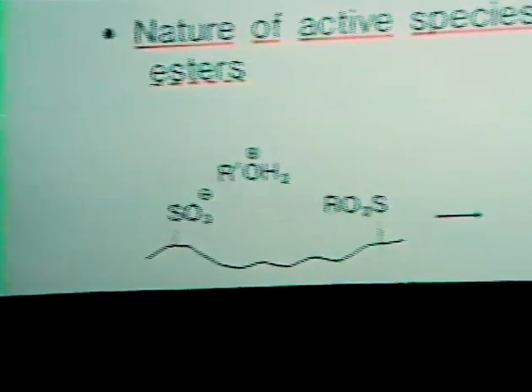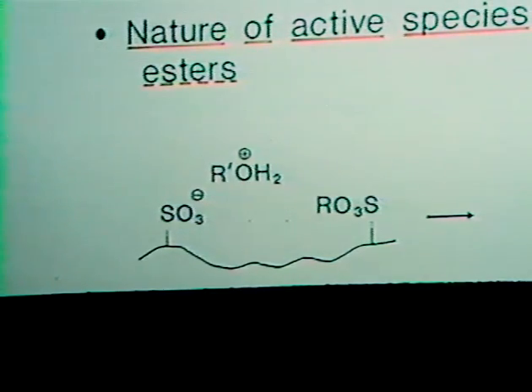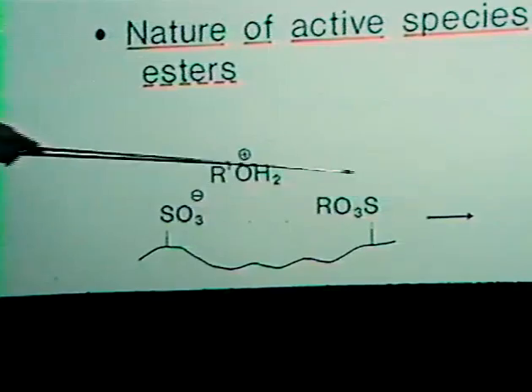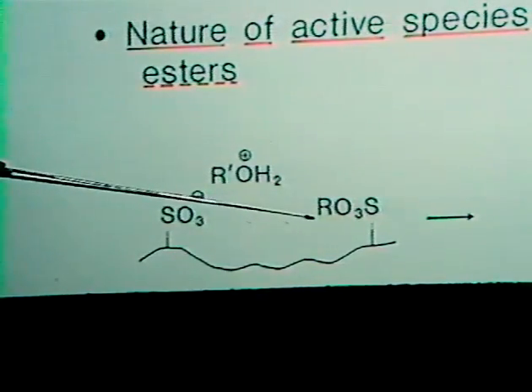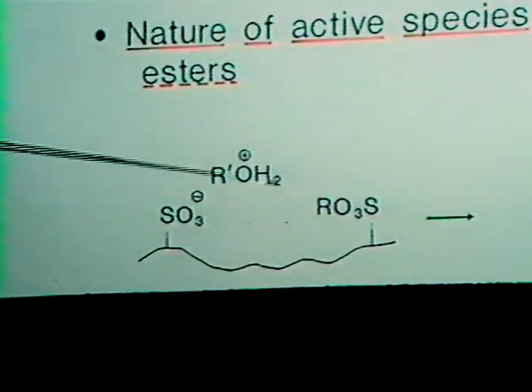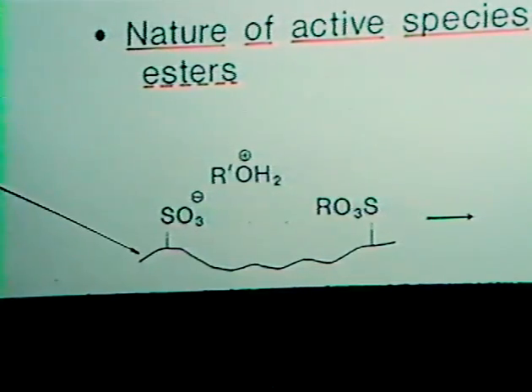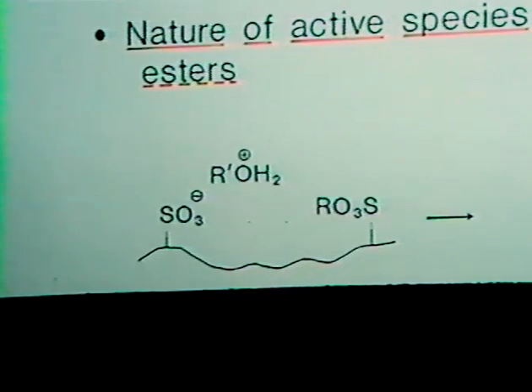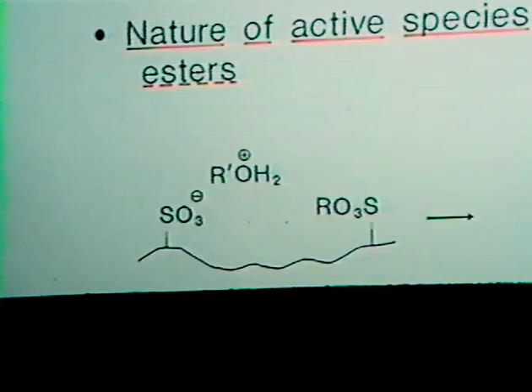The second thing that the alcohol can do with the SO3H group is to make an ester. If I have two esters, how do I make an ether? I make an ether and anhydride of two SO3H groups, possibly so. But our momentarily preferred mechanism is such that in fact one of the two alcohols, isobutanol, makes the ester. The oxonium is of course a precursor of that ester, but it reacts in the ester form with the oxonium of methanol, which sits on its counter ion. And this reaction is easily written in terms of either a concerted or stepwise process to give you the mixed ether and two SO3H groups, which regenerate the acid sites of the catalyst.